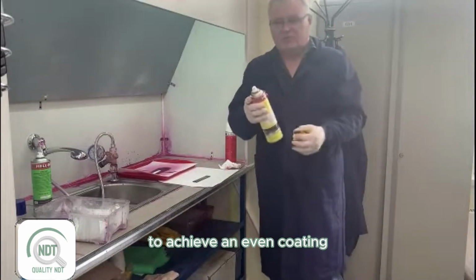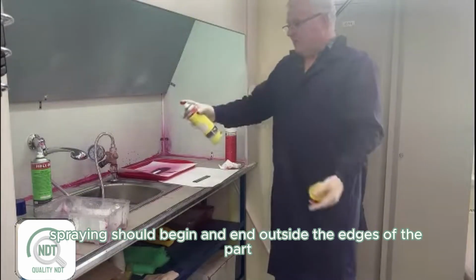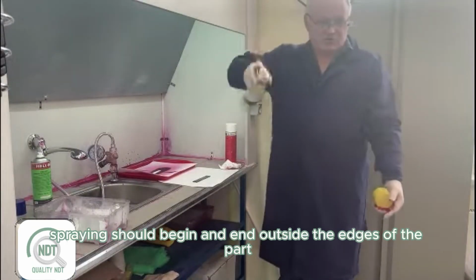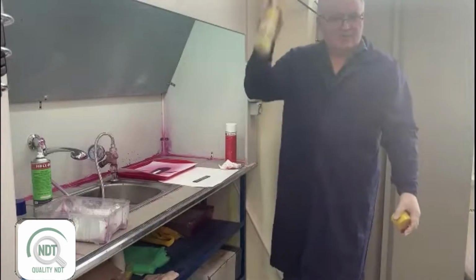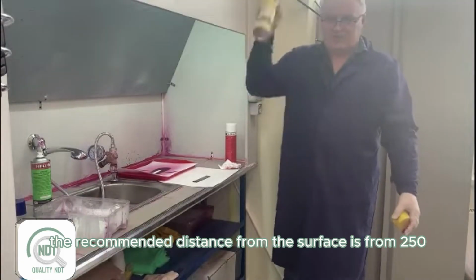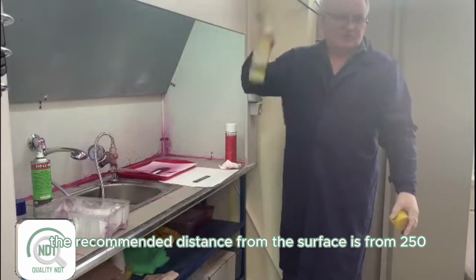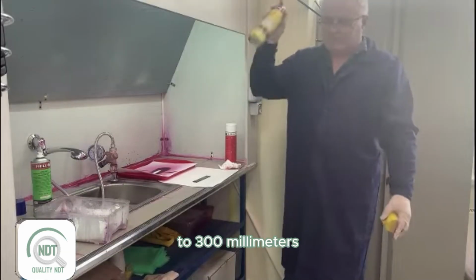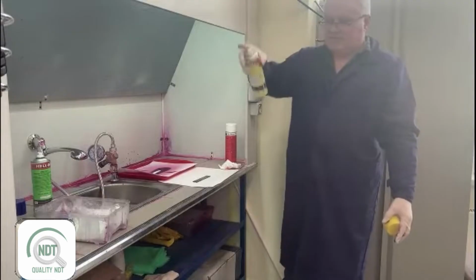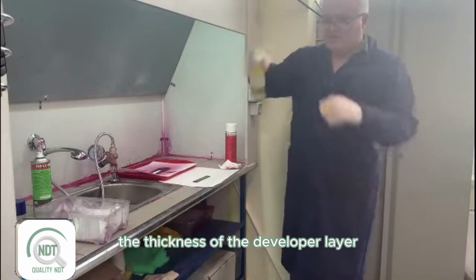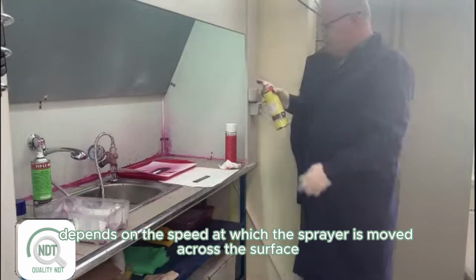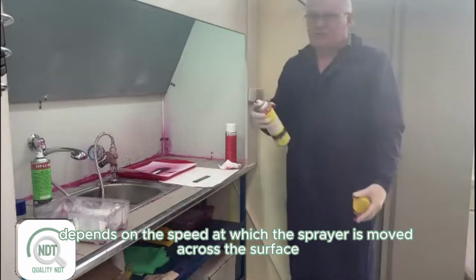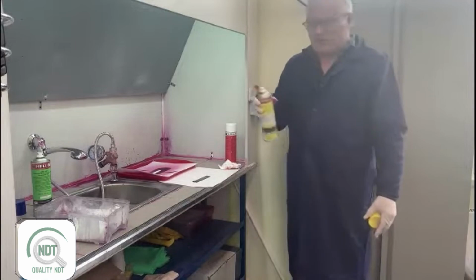To achieve an even coating, spraying should begin and end outside the edges of the part. The recommended distance from the surface is from 250 to 300 millimeters. The thickness of the developer layer depends on the speed at which the sprayer is moved across the surface.